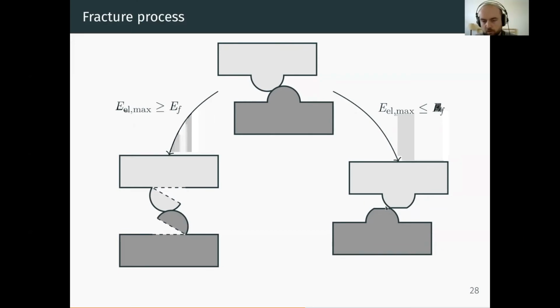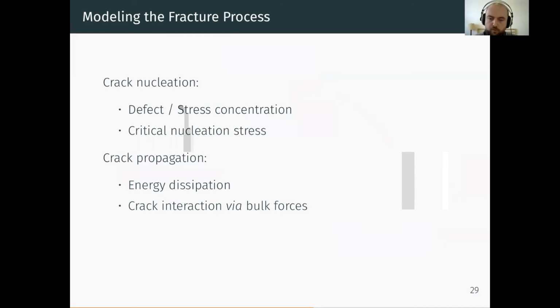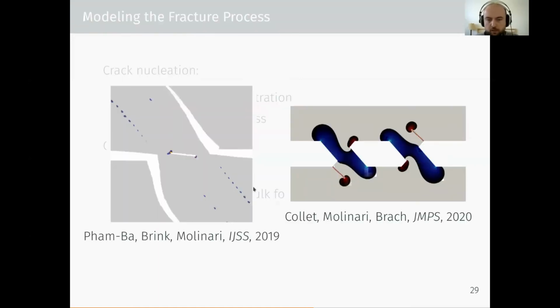But that's not the full picture, because if you want to model such a phenomenon on the scale of a rough surface with many rough contacts, you need to do crack nucleation. So either by defect or stress concentration, or if you have cohesive zone modeling, for example, you could use critical nucleation stress or other kinds of models which include crack nucleation. And you need to have crack propagation with the energy dissipation, which I just showed, and interaction via bulk forces. So this is something that can be done with molecular dynamics. It's very natural in MD to do it. And you have here the interaction between two cracks, which leads to the detachment of a single debris particle.